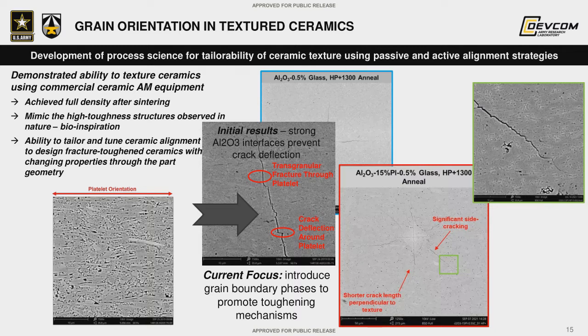What we've been able to demonstrate through this process is our ability to introduce microstructural texture at the length scale of about 1 to 10 microns, so a whole order of magnitude finer than the work we've been doing using direct ink writing, which has allowed us to create these highly aligned, almost nacre-like microstructures that have a good level of microstructural toughening to them.